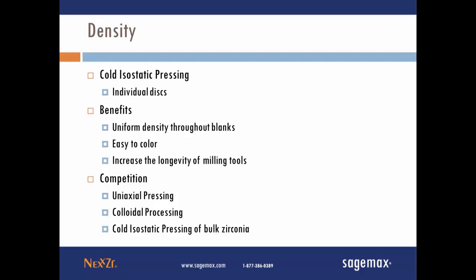This is very important. Our competition will use different ways of pressing, namely uniaxial pressing, colloidal processing, cold isostatic pressing in a bulk form, as I mentioned. There are some dramatic drawbacks to uniaxial pressing, namely pressure is applied from 2 different phases, namely the top and the bottom, and unfortunately the density is not consistent all the way through the material if you're using this type of pressing. Also, the hardness on the surface will not enable you to have good longevity of the tools. In other words, you will be using up your tools very, very quickly if you're using this type of material that is pressed like this.